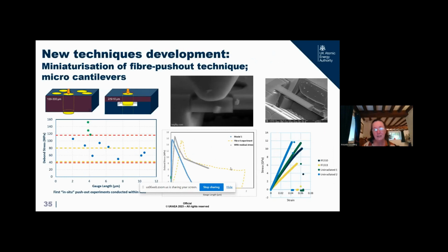And so what you're seeing in that little video up there is a fantastic high-res image of just one fiber of silicon carbide becoming debonded and sheared away from its surrounding matrix in a silicon carbide composite, and starting to look at the size of sample that we might use and the strain gauge lengths and what the results are in tests such as this one, debonding, but also microcantilevers that have been cut using focused ion beam. And the stress-strain fields are showing us that we are getting modified behavior, but not so modified that we can't still think about these materials for fusion.